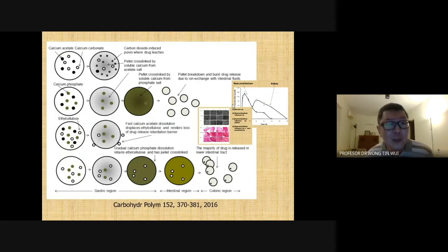And in another study, we actually challenged ourselves. Now, in this study, we developed uncoated pellets in order to deliver the drugs to the colon. Now, how to achieve it? The judicious choice of the excipient is very important. We must have the right excipients in order to form the pellets and the particles to carry the drugs. So in this study, we use alginate as the matrix material. Alginate is a polycarboxylic acid, so it has a lot of COOH functional moieties. And we incorporate the alginate matrix with ethyl cellulose and calcium phosphate.